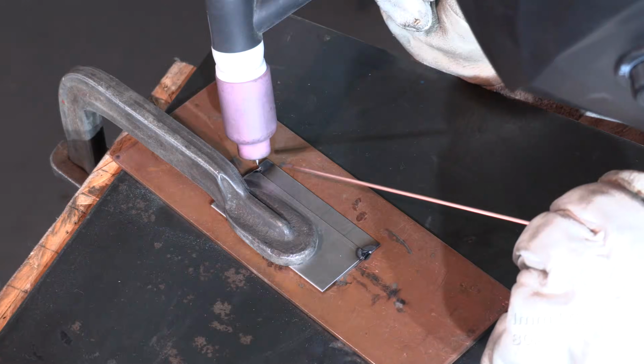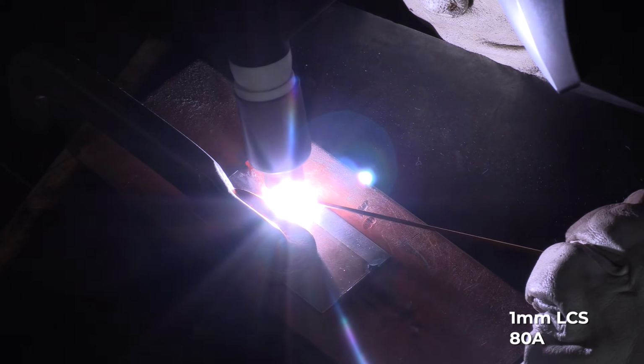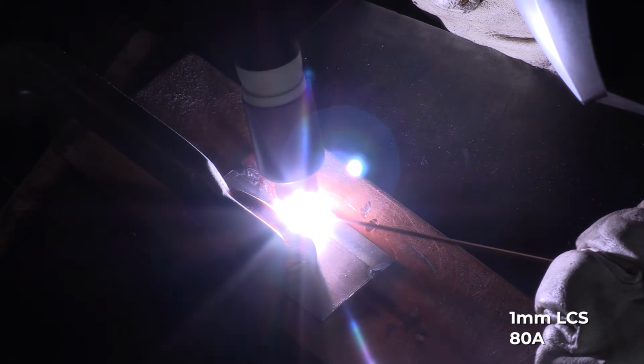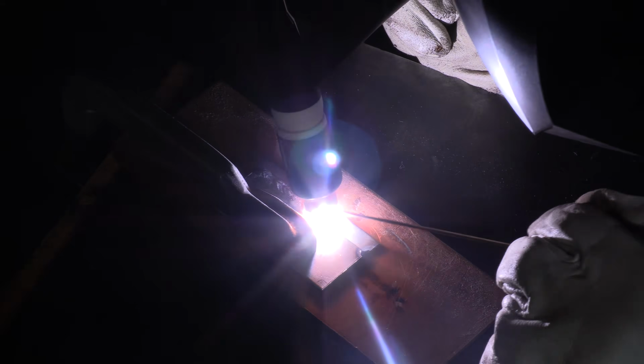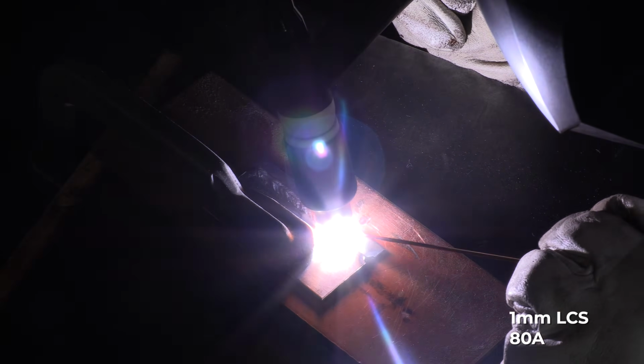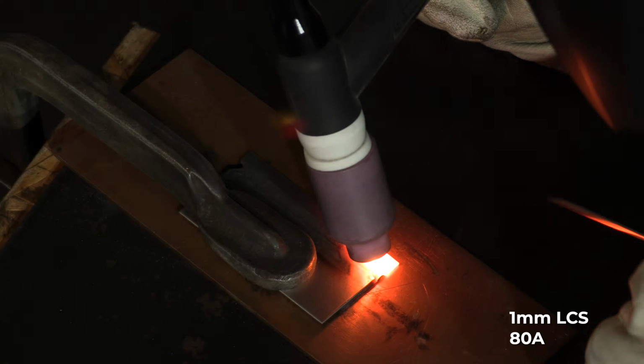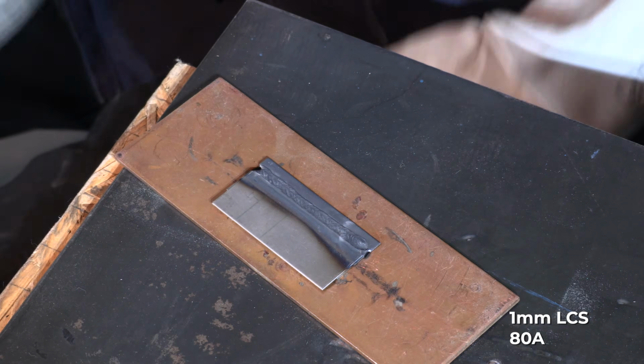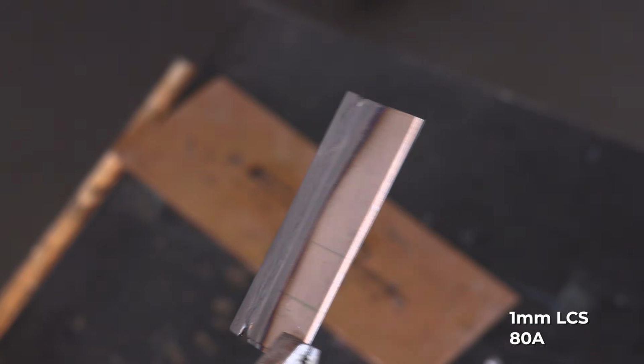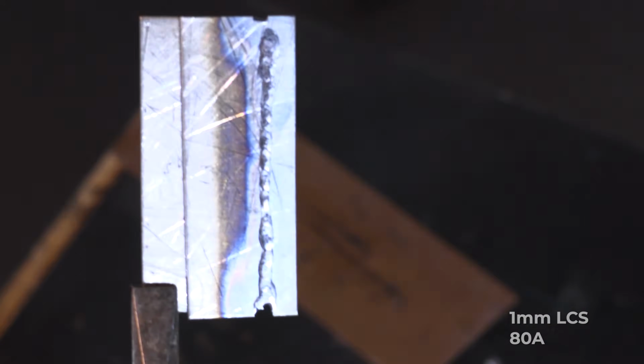Now I'm adding a copper backing to the base metal. Keeping the amps at 80, this is much better. Although it's still too hot, the copper is drawing away some of the heat and allowing me to move at a more agreeable pace than before. The weld isn't perfect and the material is still overcooked, but it's certainly better than before.